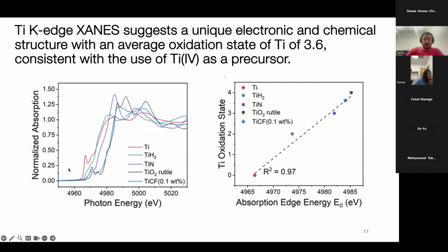And then finally, we do XANES to study the titanium oxidation state. We study the edge absorption energy for all of these different standards. So you have titanium, which has an oxidation state of 0. You have TiO2, which has an oxidation state of 4. And then you have these ones in the middle with oxidation states of 2 or 3. And we study this edge absorption energy.